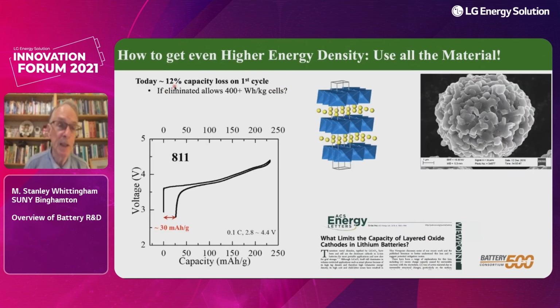So if you look at the present day cells, essentially all the NMCs lose between 10 and 15% of their capacity on the very first cycle. So we look at this, we charge this up, in this case up to about 4.4 volts, discharge it, then we never get back to our original point. And this is important capacity, because it is capacity at about 3.5 to 3.6 volts, where the electrolyte is extremely stable. So we need to recover that material. So we set out to understand what's going on there.